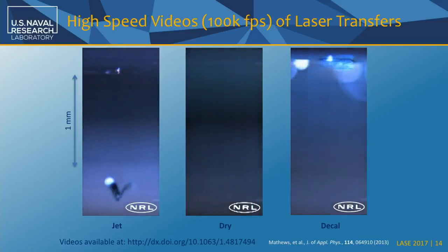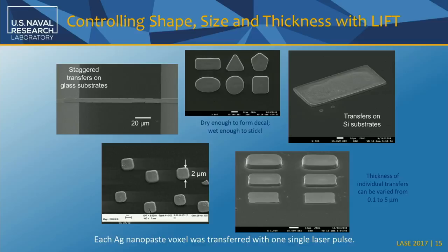Now we can vary that. So here are examples of things that we have transferred using this congruent mode. And so we can change the aperture to do that. We can also transfer larger and smaller. This is of the order of a few microns. Notice the change in thickness too. As we make larger and larger transfers, we also have to increase the thickness. If not, effectively we rip that foil apart.